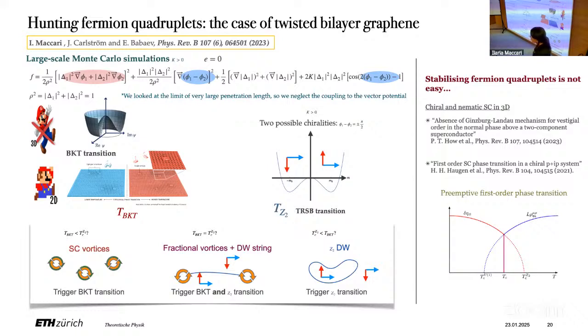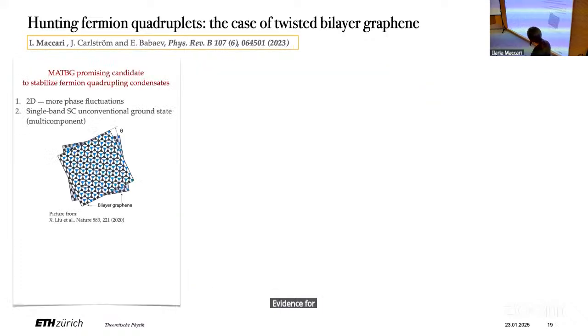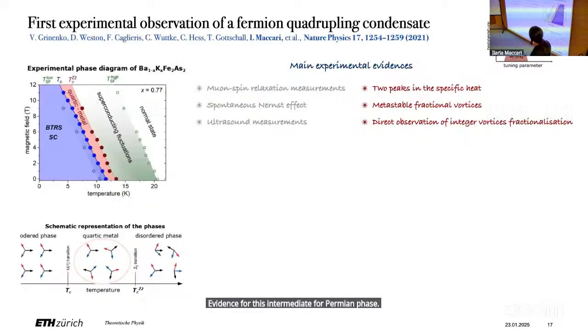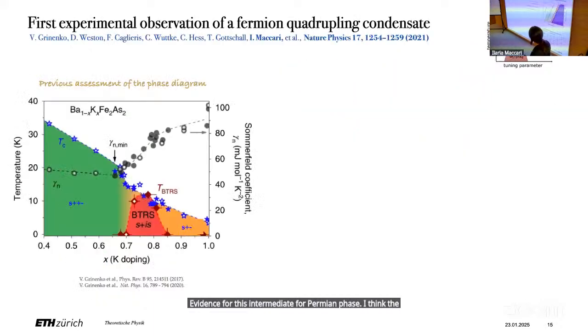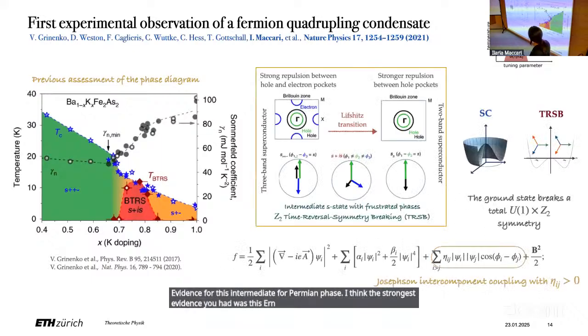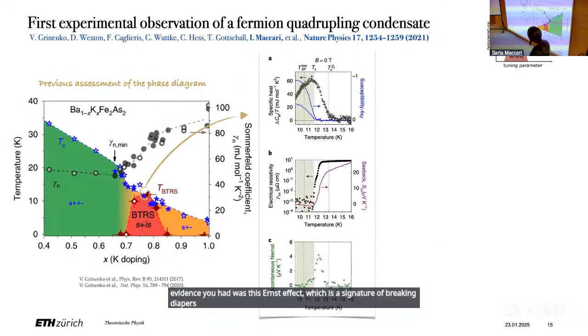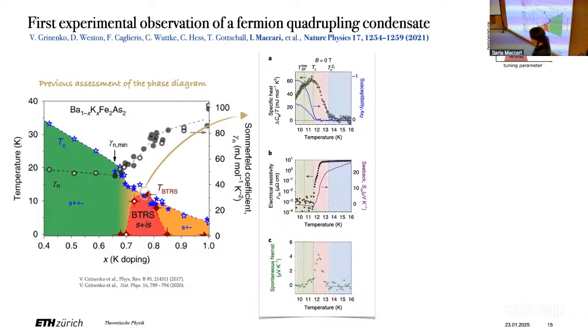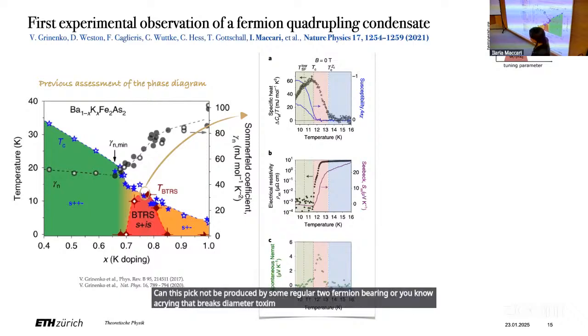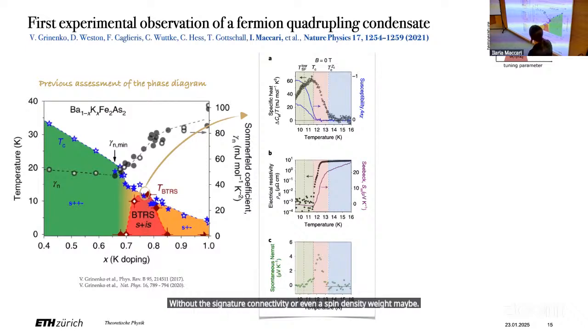Thanks for the talk. I learned a lot. I have a question about the experiment you showed, with the evidence for this intermediate fermion phase. I think the strongest evidence you had was this Nernst effect, which is a signature of breaking time reversal symmetry, right? Which occurs, you have this peak there in the middle. Can this peak not be produced by some regular two-fermion pairing, or a C-dagger-C pairing that breaks time reversal symmetry, like loop currents, without signatures of superconductivity, or even a spin density wave, maybe? So that's a very good question.